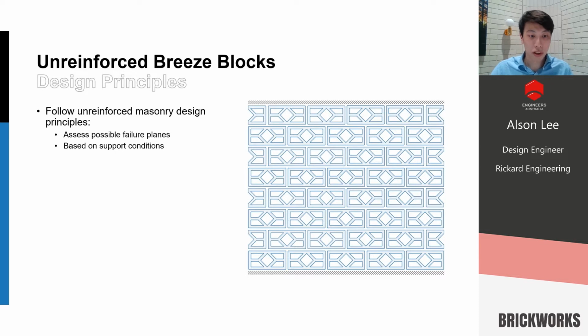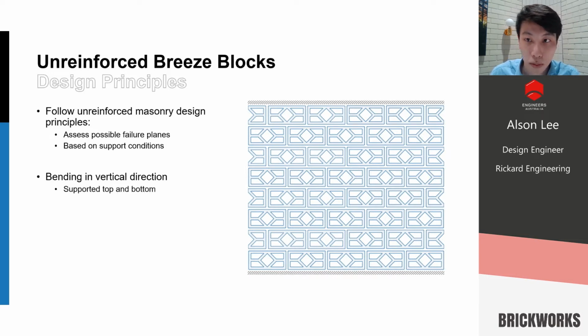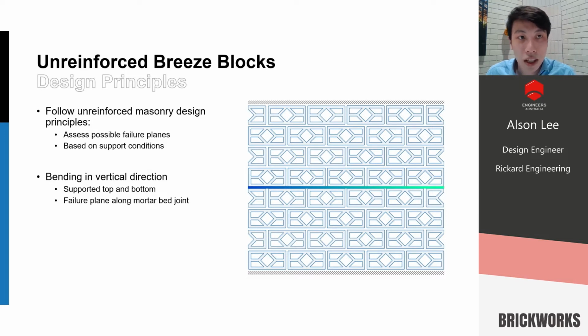From flexural behavior, we know that the areas of higher stress would tend to fail first. So in this case, when we have top and bottom supports, we are bending in the vertical direction. When we are loading this wall, we're expecting a failure plane horizontally along the mortar bed joint. This is important in a few ways. The bed joint is the most critical aspect of most of our designs, both unreinforced and reinforced. So we're looking for ways to address this weakness and how to strengthen and build walls.